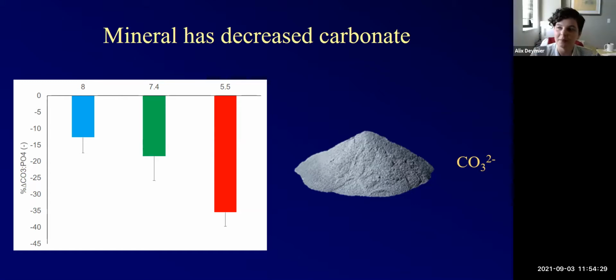Yeah, so what I think might be happening, and this is all hypothesis, is that it's all about the crack initiation. In the situation where we're doing 3-point bending, it's not so much about the propagation. These bones seem to fail very abruptly, but it's all about initiation. And since the initiation is going to be happening at the surface and not within the interior, we definitely see that it's on that tensile side of the bone. Probably whatever modification is happening on that most outer surface of the bone is stopping that first initiation, but once it's there, it just propagates. So that's my theory as to why the interior may not matter as much as the exterior shell.